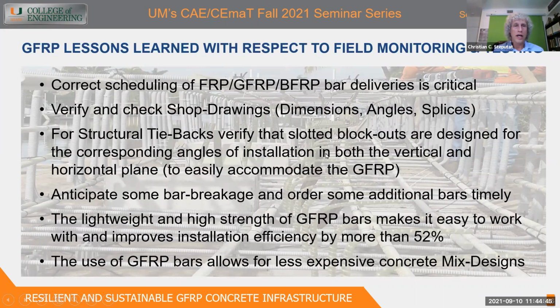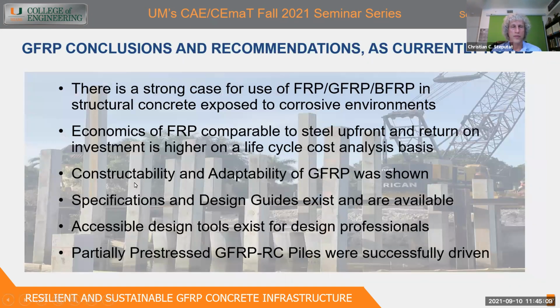Now, lessons learned from this, of course, is you've got to be aware of your in-plane, out-of-plane bending, and you also got to anticipate some of the bar breakage ahead of time. So order your bars ahead of time because it can sometimes have longer lead times than steel rebar. Installation efficiency was about 52% better than using steel, or faster, less labor required, less tired workers, possibly fewer OSHA-recordable accidents, and basically splices could be made.